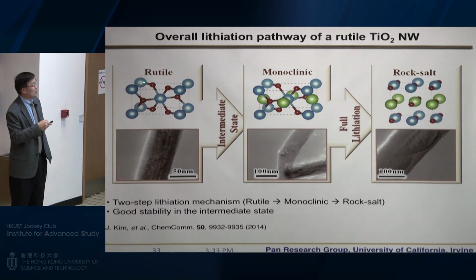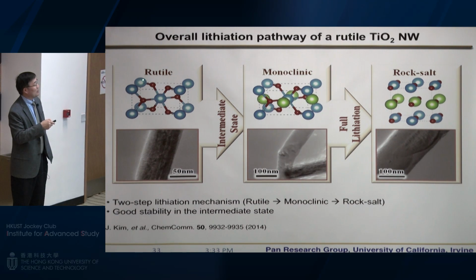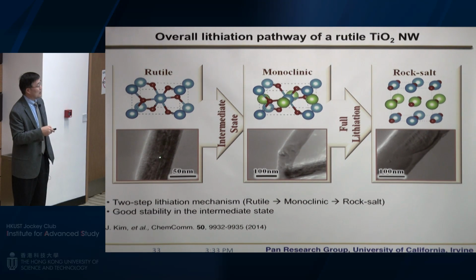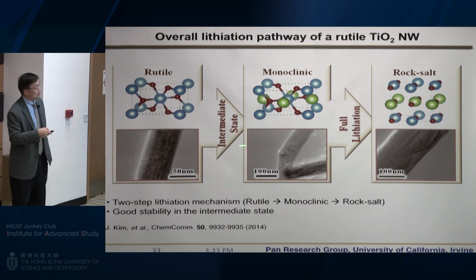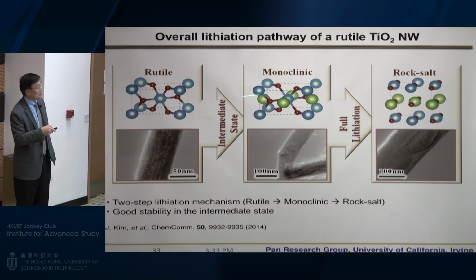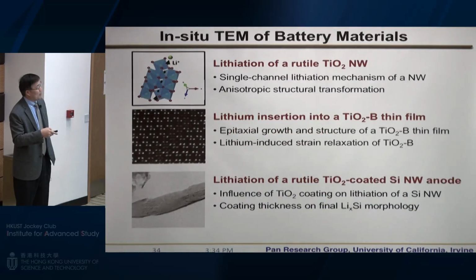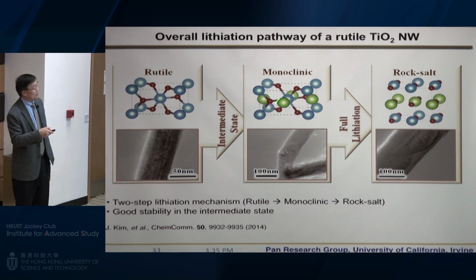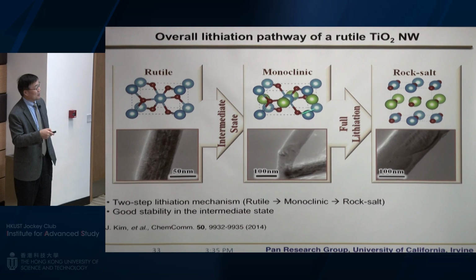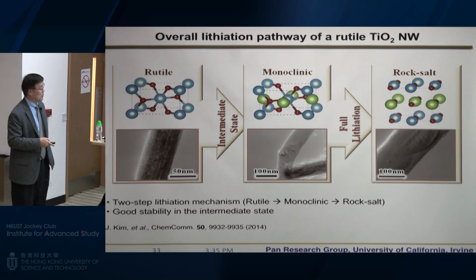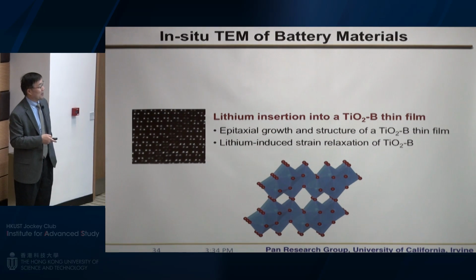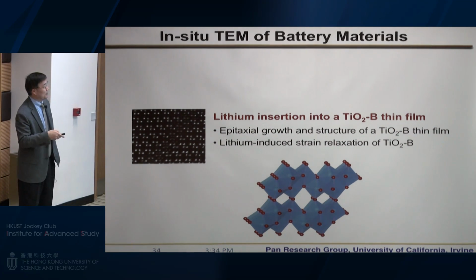This is the transition during the insertion of lithium in TiO2 rutile nanowire. There will be two kinds of change: volume change, and also phase change. Phase change has two steps. One is from rutile to monoclinic. This is reversible, but an intermediate change. And then the second phase transition is not reversible. This introduces more defects and is also destructive. Sangju just finished, but he's now back in Korea doing military service.